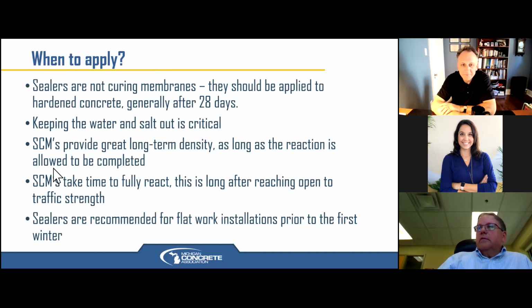When do you apply a sealer? The right time to put a sealer on, they don't really consider them curing membranes, but they should be applied to hardened concrete after about 28 days. They keep the water and the salt out. The supplemental cements provide great long-term density as long as the reaction is allowed to be completed. But we built a lot of projects in the fall, and at the end of that fall, the true density hasn't been reached yet. It's strong enough to handle the traffic loading, but it's not impermeable. It hasn't sealed itself up enough to be a long-term, seal-proof material.